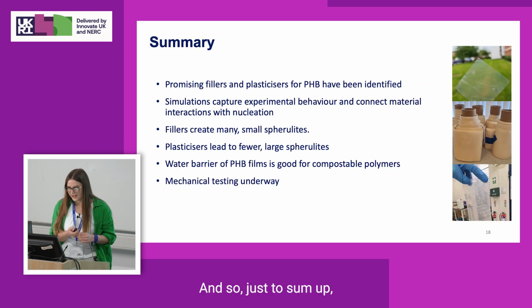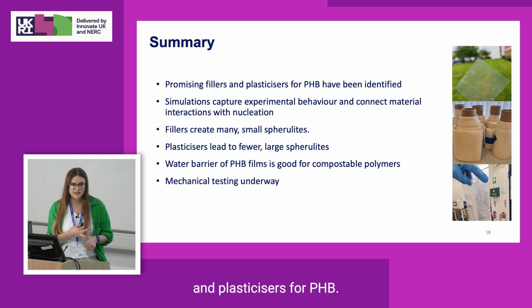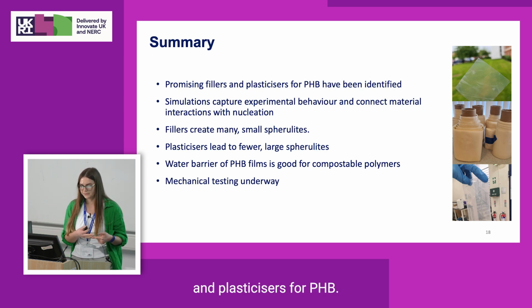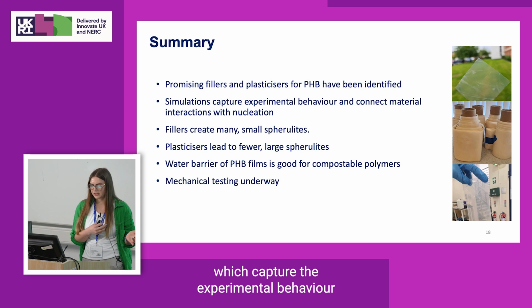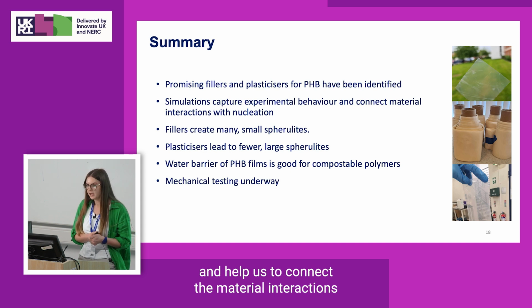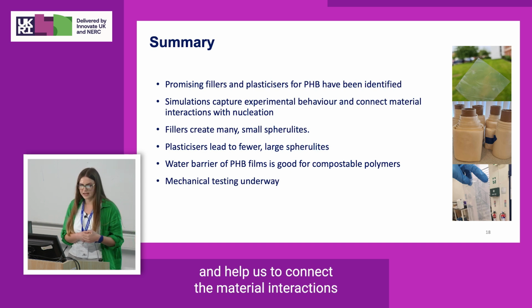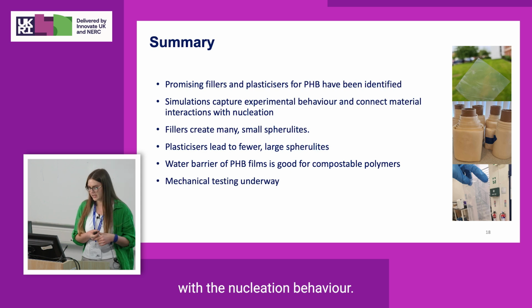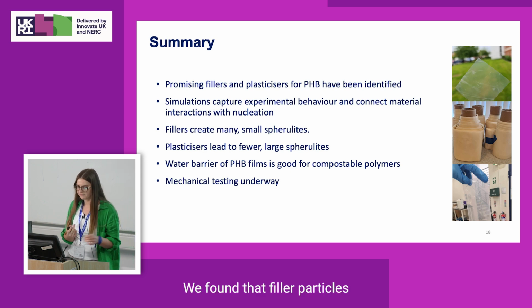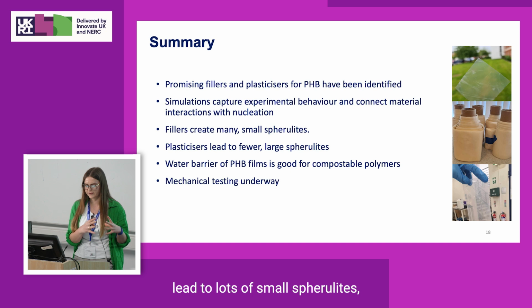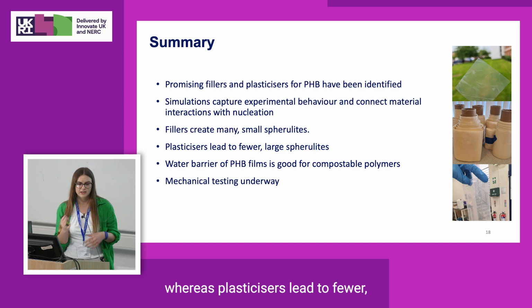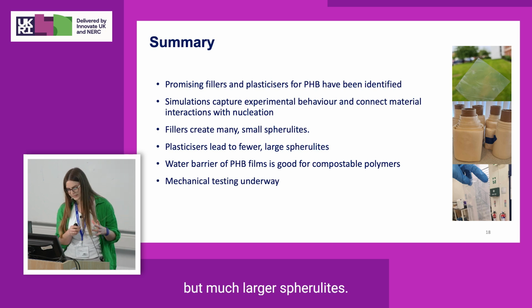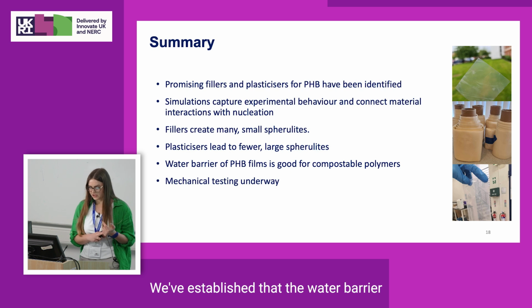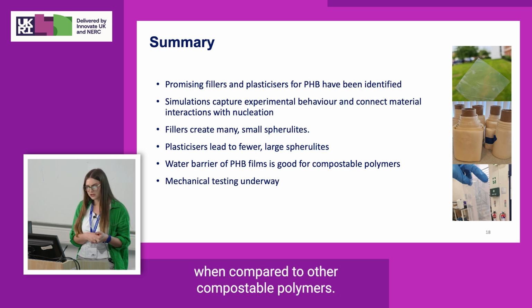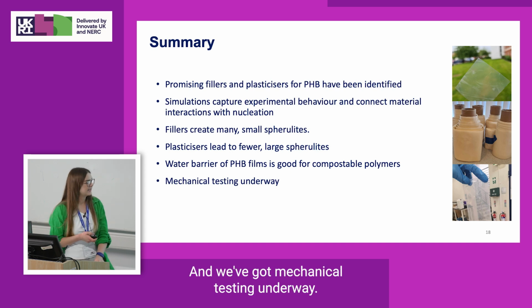And so just to sum up, we've identified some really promising fillers and plasticizers for PHB. We've got simulations which capture the experimental behavior and help us to connect the material interactions with the nucleation behavior. Found that filler particles lead to lots of small spherulites, whereas plasticizers lead to fewer but much larger spherulites. We've established that the water barrier of PHB film is actually pretty good when compared to other compostable polymers, and we've got mechanical testing underway.